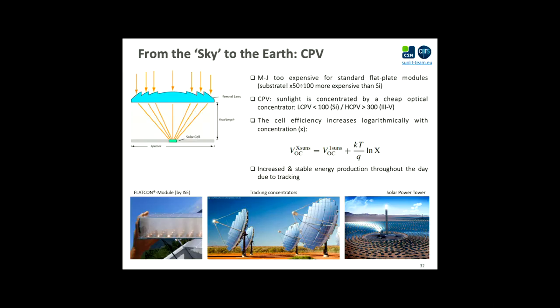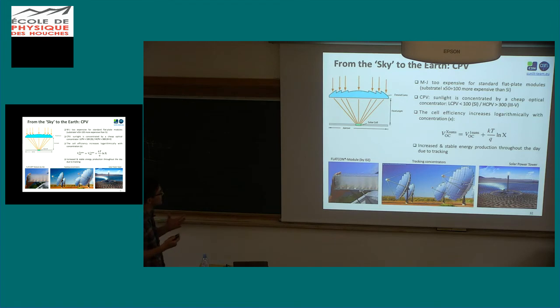And so what we do instead is to use concentrating photovoltaics. So the idea is simple. Instead of having a large panel, you have a large optical element such as a Fresnel lens or a big mirror that can focus the light inside a very tiny, few millimeter square, super expensive III-V solar cell here. And so by doing so, there are different implementations of this concept, small modules or big things. You can reduce the price, and you also gain in efficiency, because in this case you have a density of photogenerated carriers way higher than at one sun. It depends on the concentration, and by doing so you can increase the VOC, as we saw already. When you have a high density of photogenerated carriers, you increase logarithmically the VOC.